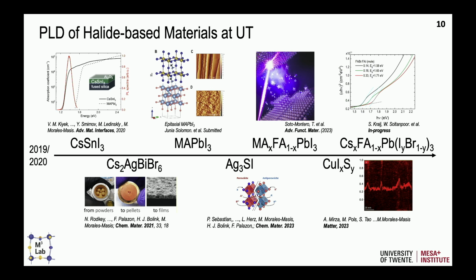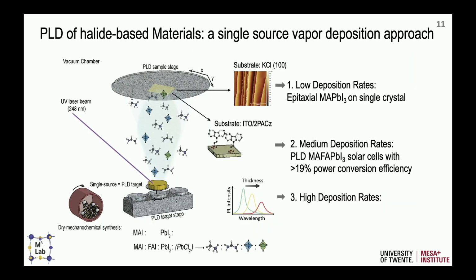So we started this around 2019, and this is what we have been demonstrating. And of course, some of the new work is based on wide bandgap perovskites for the future development of tandems. But I'm going to talk mainly about the methylammonium formamidinium lead iodide in this case. And what I want to show you a bit is our developments. This is going to go much more in detail, but to cover the different stages of the audience, we do quite fundamental work when we go with very low deposition rates and try to get to epitaxial halide perovskites. We do what I call medium deposition rates to do, for example, solar cell devices. And then we go for very high deposition rates to go to high TRL and actually make this a bit more interesting for industry in the future.